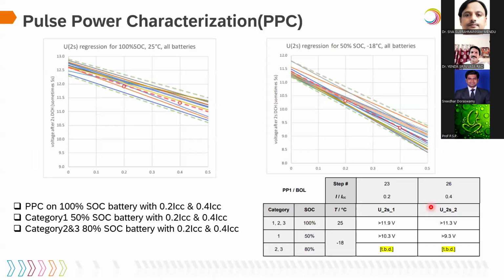So coming to the pulse power characterization, it is based upon the state of charge of the batteries: 100%, 50%, 80%. The 80% has not yet been determined. By March 2025, this may be frozen. At 100% SOC and a small current rate, like 0.2 amps, the voltage should be greater than 11.9 volts. The 12-volt system should be more than 11.9. And at 0.4 amps, it should be more than 11.3 volts. Similarly, at 50% SOC, it should be greater than 10.3 volts for 0.2, and for 0.4 amps it should be greater than 9.3. So these challenges are not that difficult. These are achievable.